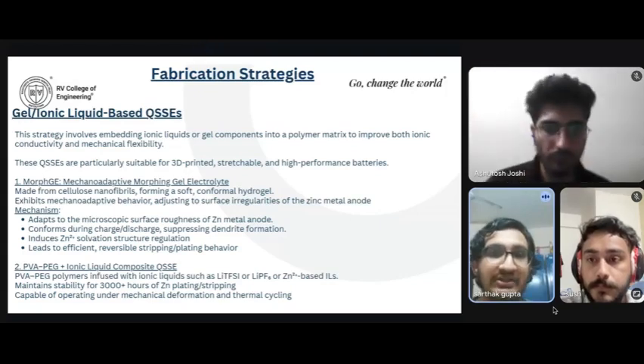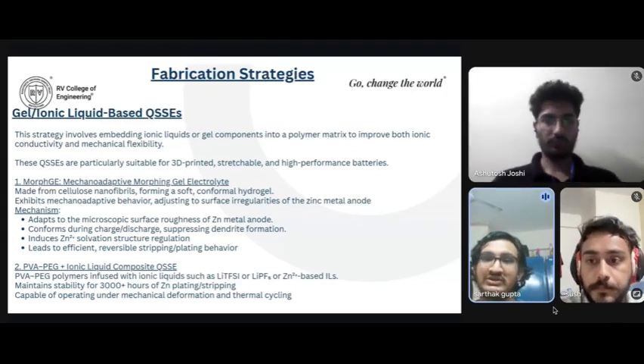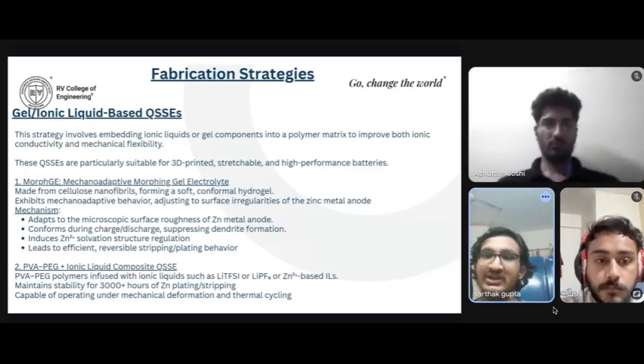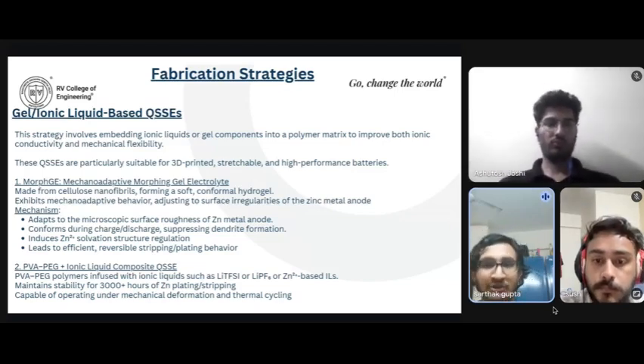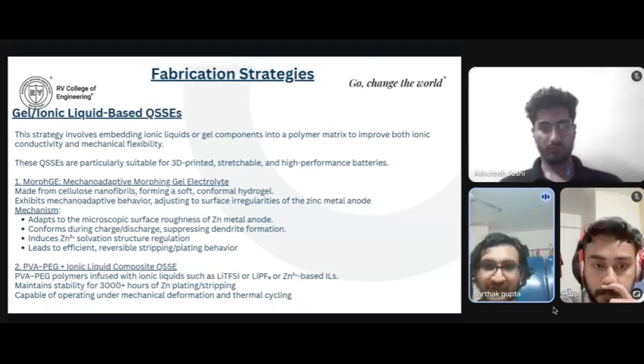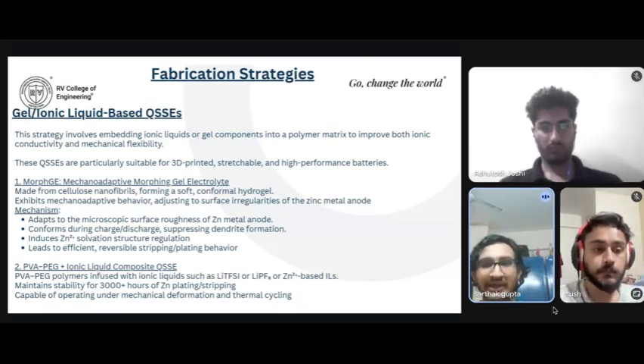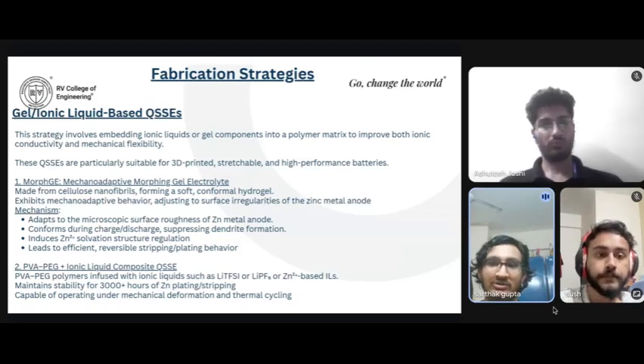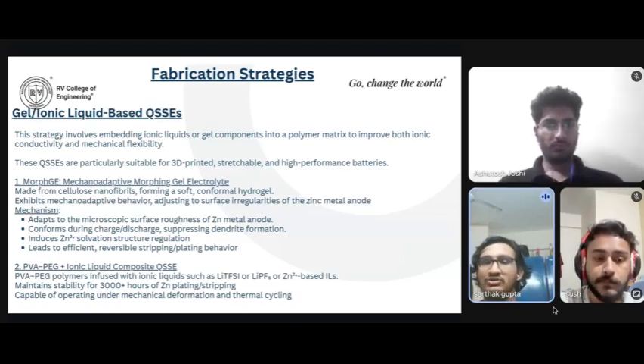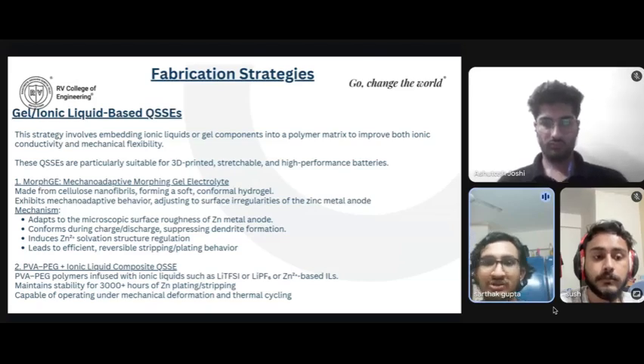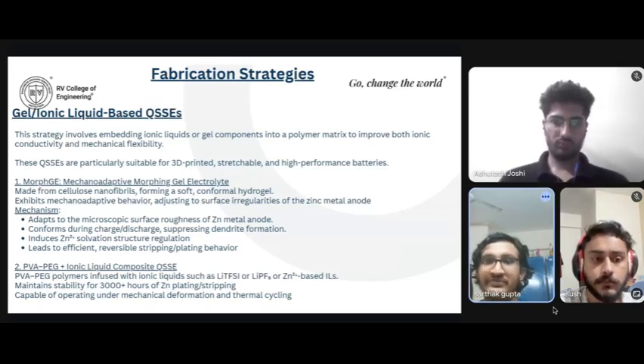So gel ionic basically uses ionic liquids such as LiTFSI, LiPF6 and others that are embedded into polymer matrices like PVA, PEG. These ionic liquids offer a wide electrochemical stability window and excellent thermal stability, right? They are combined with polymers to form printable, moldable QSSEs. So these can be formed into gels or electrolytes that are printable, and we can also use them in the molding of batteries, so that whatever the shape of the battery, these can easily fit.